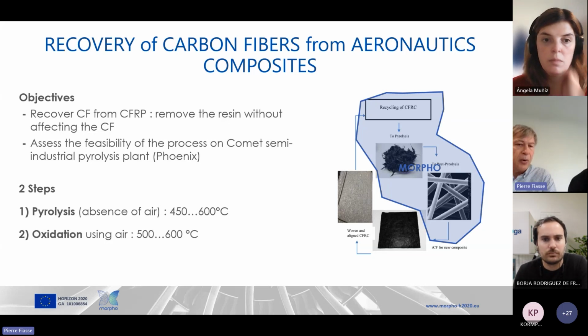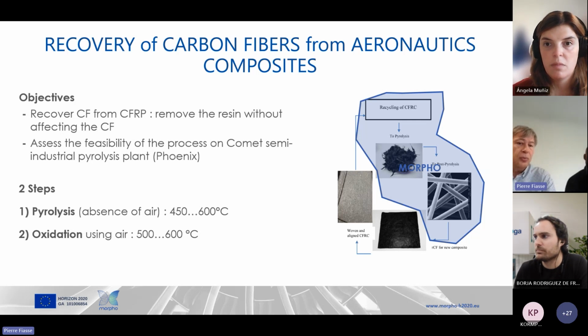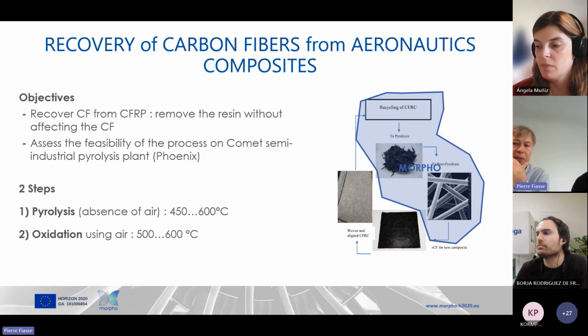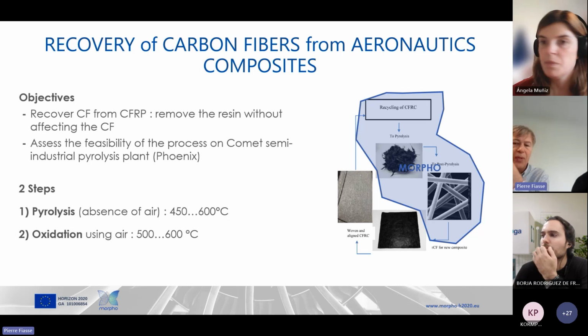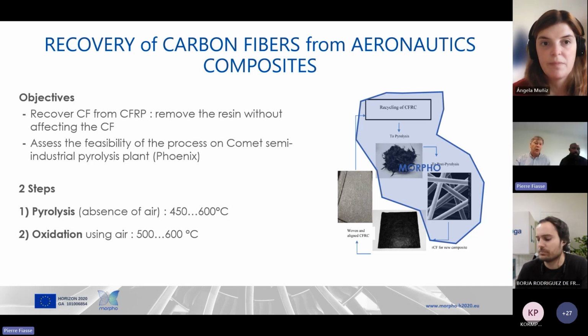So two steps: pyrolysis, with a range of temperature to define between 450 degrees and 600 degrees, and then oxidation with 500 to 600 degrees, typically. What we haven't done in the project is the next step, to obtain the resin and then transform them in new composites. I think that the next speaker will elaborate a little bit more on these aspects.